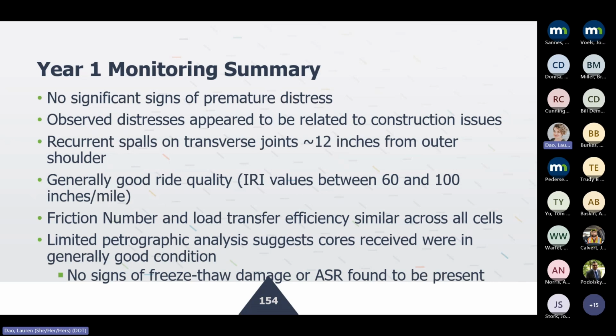And then there was some limited petrographic analysis performed by AET. And then most of the cores seemed to be in good condition. There were no signs of freeze-thaw damage or ASR damage. But one thing they did note was they did see carbonation at depths that exceed typical expectations for 1 year. 1 year after construction, you would expect maybe 1 millimeter of carbonation, but they saw carbonation at depths like 6 to 7 millimeters.